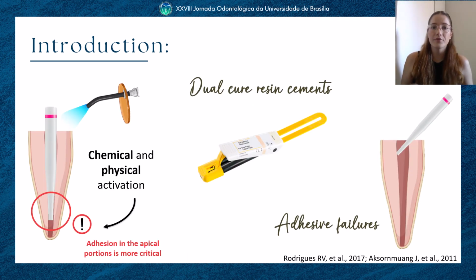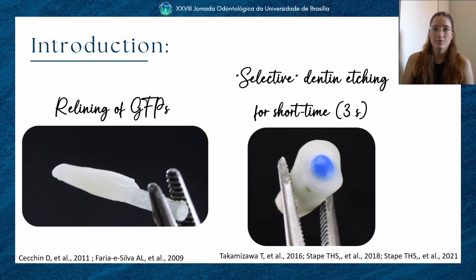A lower degree of conversion, DC, is observed in the deepest region of the root canal, and consequently, lower mechanical properties. Therefore, the use of dual-cure resin cements is indicated, in which the chemical polymerization is important in the deeper portions of the root. Since chemical polymerization is less effective, adhesion in this apical portion is more critical, and that can lead to adhesive failures.